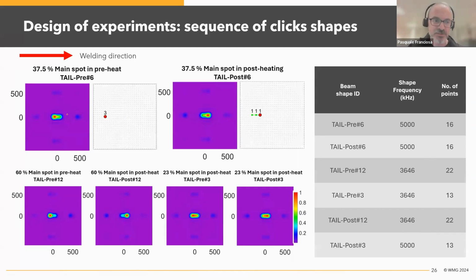The second set of experiments is to have a more elliptical shape with the peak intensity either to the rear or to the front. You can see the animation of those clicks. One click again corresponds to one diffraction pattern. And interestingly, you can see a 6 there. It means that the diffraction pattern in that position is enabled 6 times more compared to the others. In terms of time, the diffraction pattern stays on the workpiece 6 times longer than at the other points. That's why, if you combine all the diffraction patterns, you eventually see a shape that looks like what you see on the screen. So with that logic, we generated those 6 profiles.